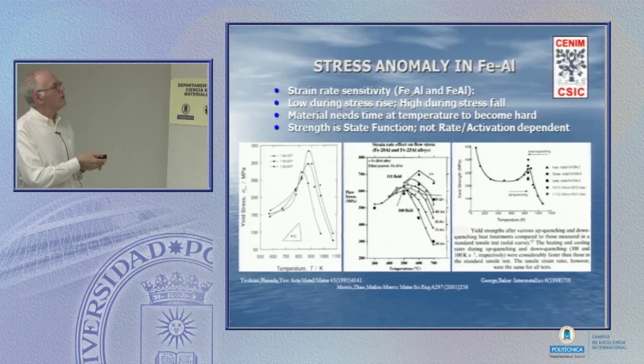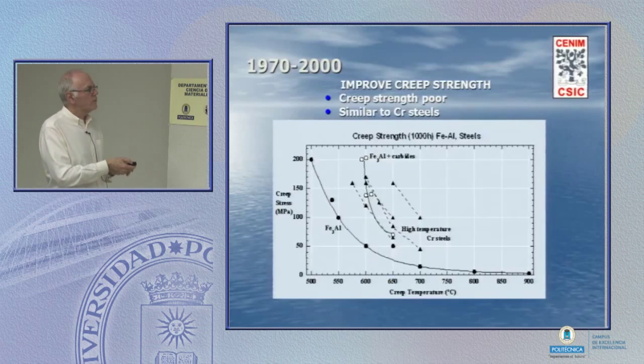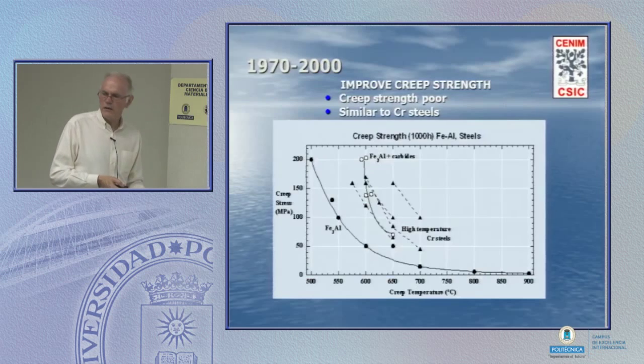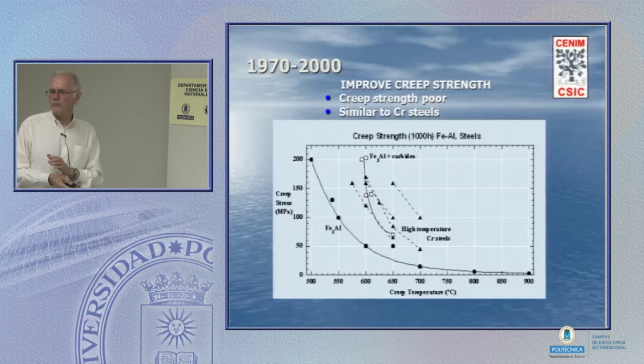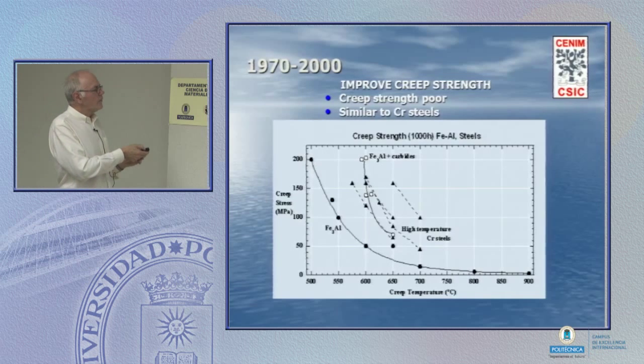Now, unfortunately, when we look at creep strength, and what I'm saying here applies exactly to all steels, the iron aluminides are ferritic steels with a lot of aluminium. What we're looking at here is the stress that we can apply for a creep life of 1,000 hours as a function of temperature. If I apply a high creep stress, that's okay at low temperature, below about 500 Celsius, but when I get to 600, or especially when I get to 700 Celsius, the creep strength has come down enormously.